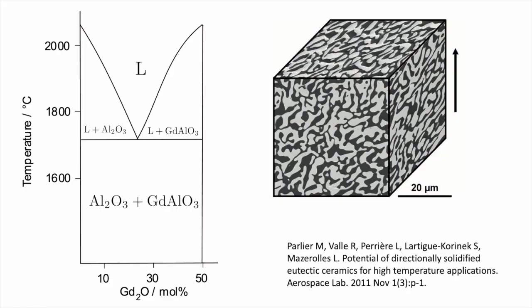Now, all the examples that I've given you so far have been from metallic elements, but you know, eutectics also happen in oxides and ceramics. So here, for example, is a phase diagram between alumina and the gadolinium aluminium oxide. Here we are plotting the amount of gadolinium oxide, and we have a eutectic here.